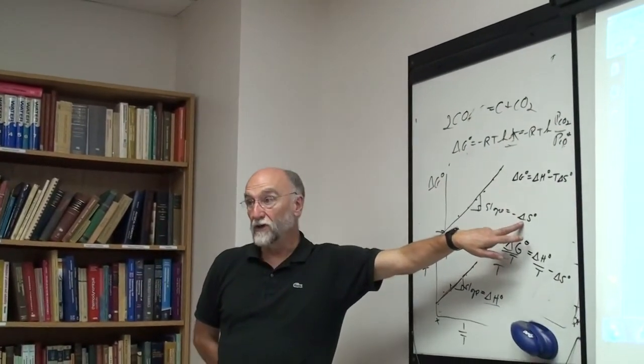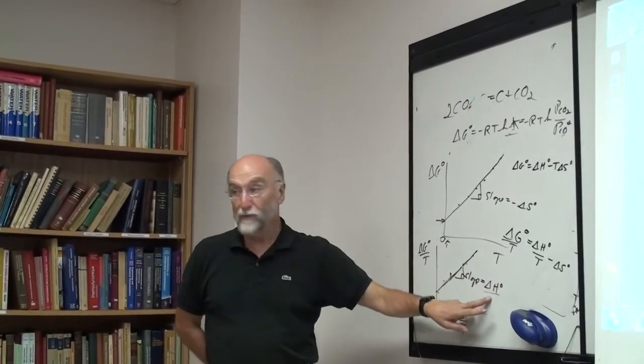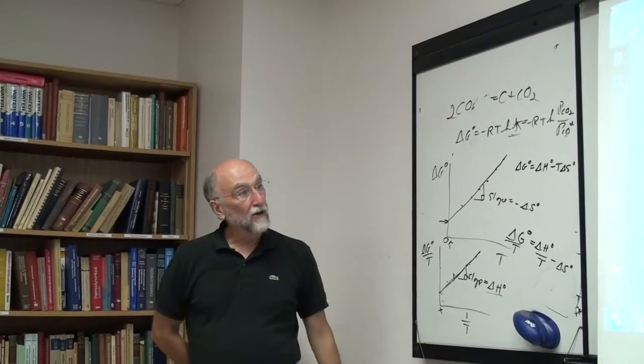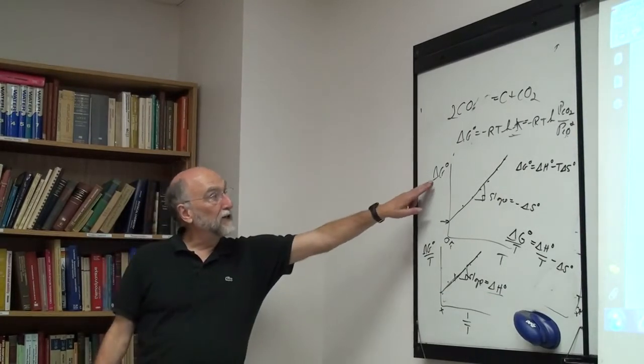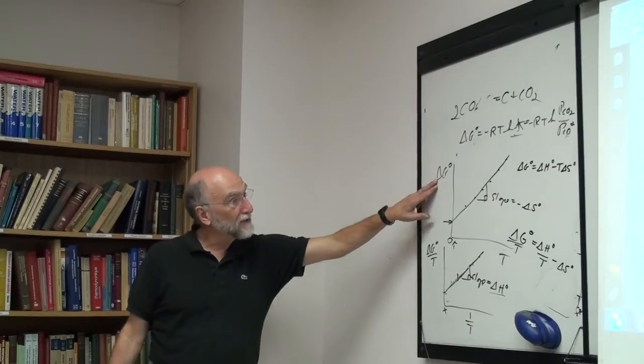You'll often see in your work that somebody's measured the electrochemical cell, by the way. You can use electrochemical cells for measuring activity, for example. If your cell reaction, we'll do this later, is for the material going into solution, you're measuring the RT log activity, you're measuring the partial Gibbs energy electrochemically. If this is the partial Gibbs energy, RT log activity of a component, then the slope is the partial entropy. And the slope of this line is the partial enthalpy.